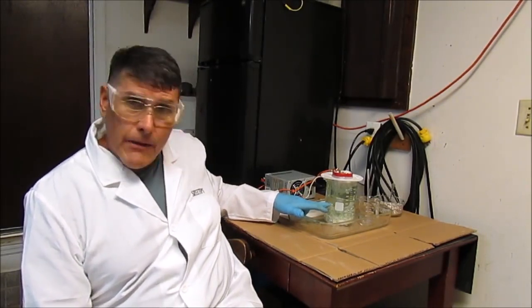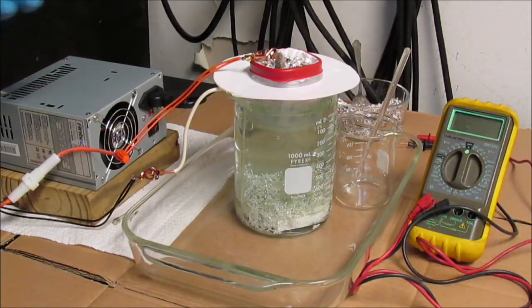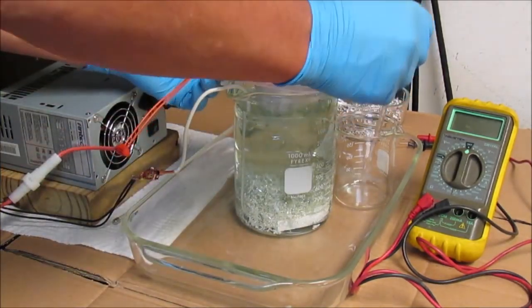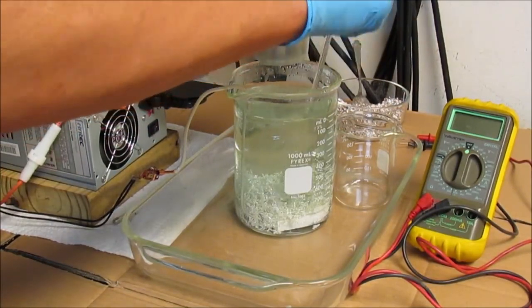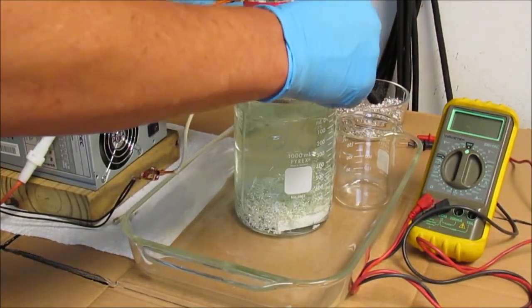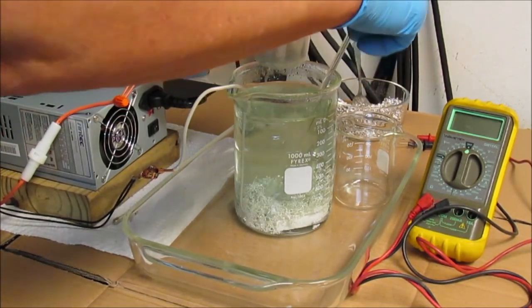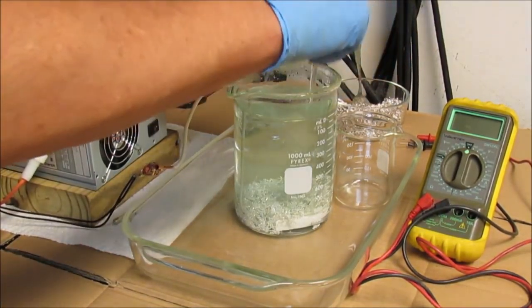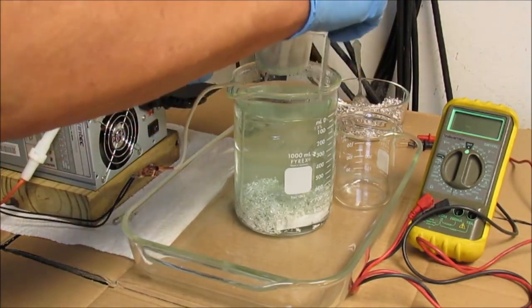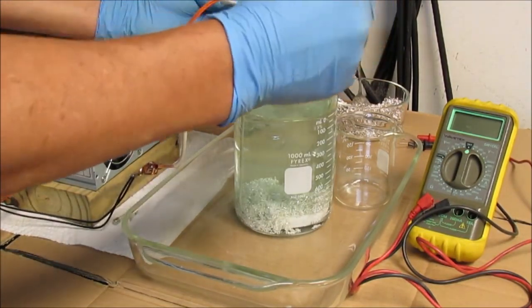And I've only been here about half an hour since I knocked those crystals down. So the crystals have got to be checked at least hourly and knocked down. Otherwise, they'll make contact with the anode basket, burn a hole through it, and contaminate the pure silver crystal. It's been about 45 minutes since the last time I tamped these crystals down. They're growing rapidly, and this has to be done every hour. If we don't do this, the crystals will contact that basket, burn a hole through the bag, and contaminate the batch of silver. So they've got to be knocked down every hour.